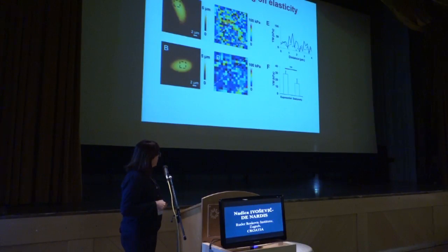It's interesting to say that those algal cells, a naked species that possess only the plasma membrane, have a Young's modulus in the order of magnitude of kilopascal, while, for example, for the cells that possess a silica cell wall, that Young's modulus is 3 orders of magnitude higher, like in megapascal.